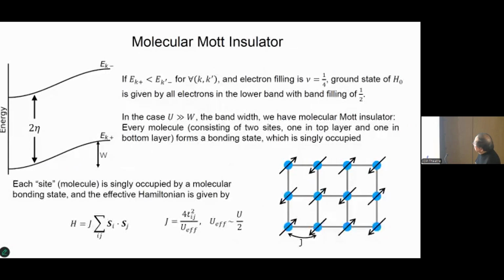But if eta is large, let's consider this case. We have a two-band system. This is the bonding band, and this is the anti-bonding band. If this band splitting is large, and I consider one electron on average per site in the double layer system, then I can forget about the anti-bonding band and focus on this. Of course, because of the Coulomb interaction, you cannot put the electron just freely here. But I can drop all this because it becomes irrelevant.